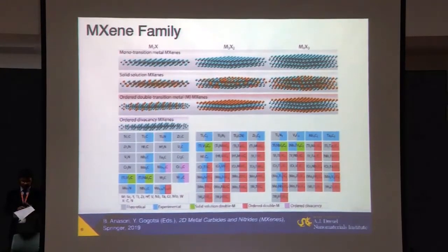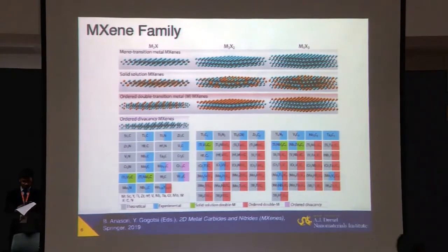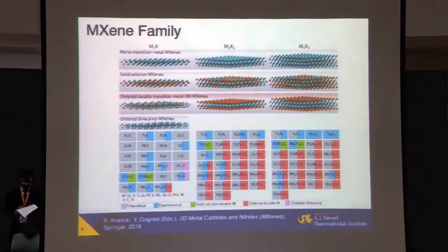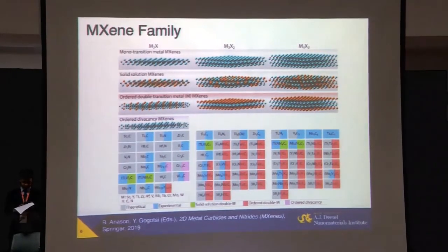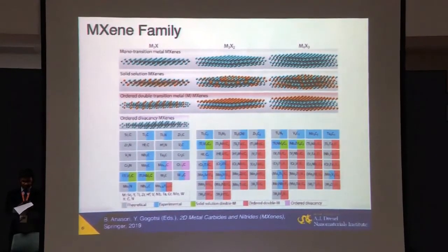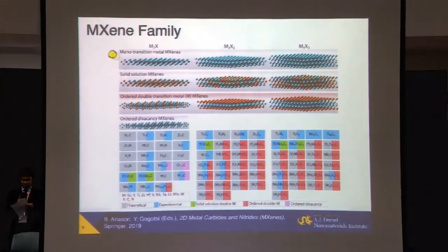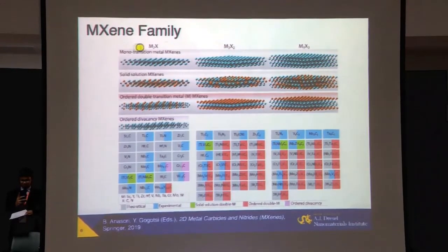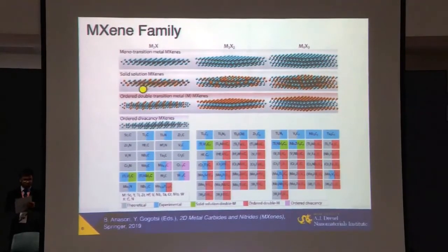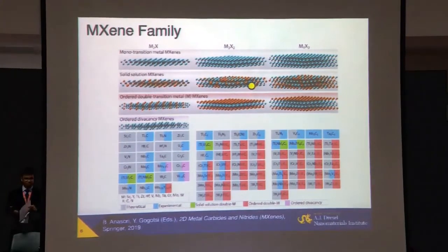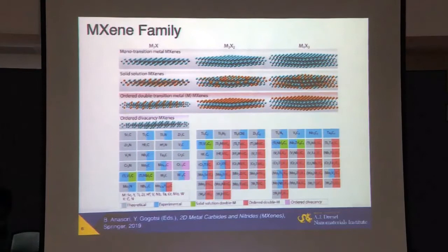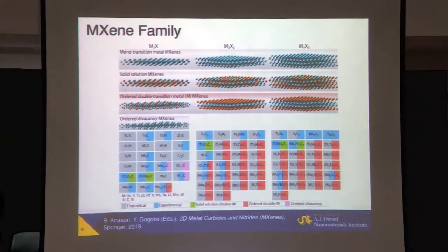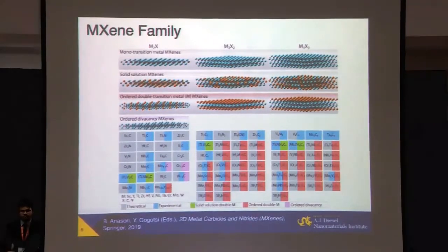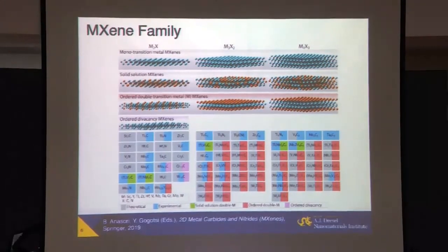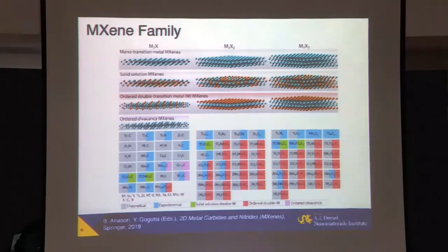So what do we have nowadays? We actually have a family with already at least 30 stoichiometric two-dimensional structures produced experimentally in the lab, and at least 100 possible. So those are these mono-transition metal MXenes, as I mentioned, M2X, M3X2, M4X3. But they can form solid solutions. You can actually, on the M side, mix different atoms, for example vanadium and titanium, or molybdenum and tungsten. And they form really any number of solid solutions. So we're facing an infinite number of compositions that we can design.